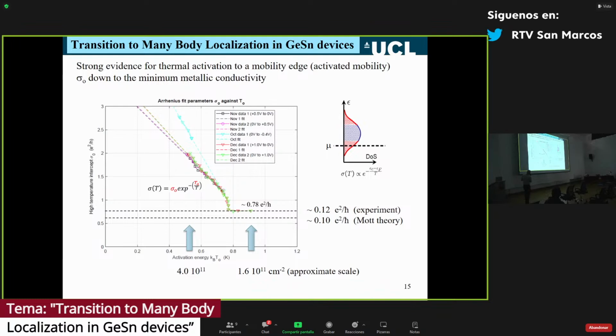And if you plot them all out, this is sigma 0 in units of e squared over h as a function of T0. So that's the activation energy, T0. They all sit on a universal curve, and it was quite striking initially. What happens is this prefactor comes down and just gets anchored at this point. It's about 0.78 e squared over h. It's very, very clear in this system.